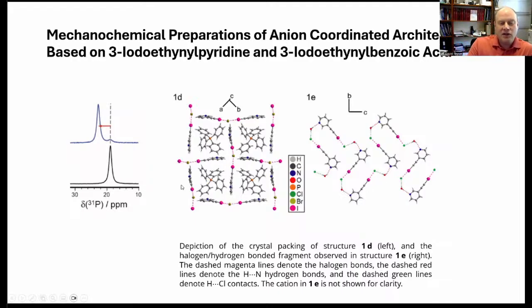And again, on the left here, just emphasizing the clear shifts that we see upon co-crystal formation. So the bottom trace would be our phosphorus resonance for our pure starting material. The top trace here, we have formation of a co-crystalline product, and you can even see now a trace of starting material left over. So a very easy way to quantitatively monitor what's going on as a result of your ball milling.